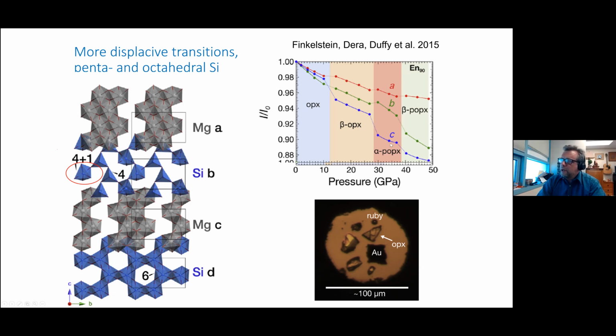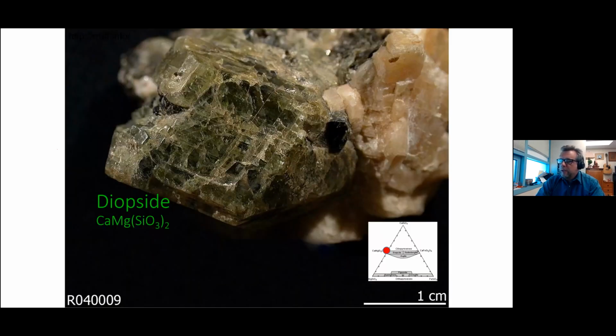So when you lower pressure, you get back transformations. The only way to characterize the structure and property of these unusual phases that have these atypical hypervalent silicon coordinations is to do it in situ while the sample is still pressurized. We went to look at compositions with higher calcium content. So this is diopside, which is half calcium and half magnesium.